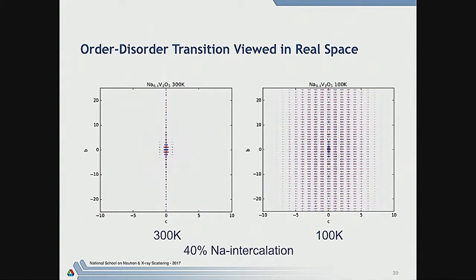If we go below this order-disorder transition where we had the Bragg peaks, that Bragg peak intensity is also included in the PDF, and it's showing us that these same short-range correlations persist over much longer range. We're actually imaging, effectively, an order-disorder transition in real space using the diffuse scattering without having done any modeling, okay? So this is why I think this is the way to go, because with diffuse scattering, you can't tell exactly what's going on just by looking at it without doing some modeling. With this PDF, you can automatically infer some things without having done any modeling.